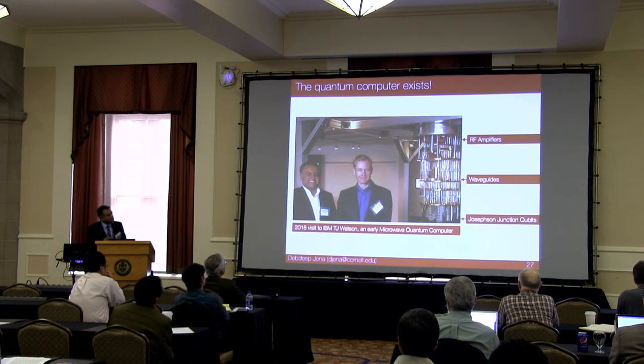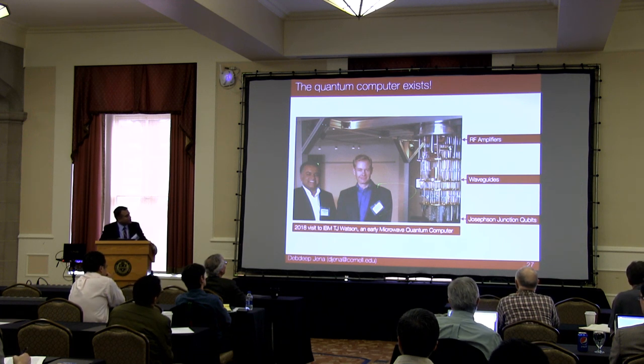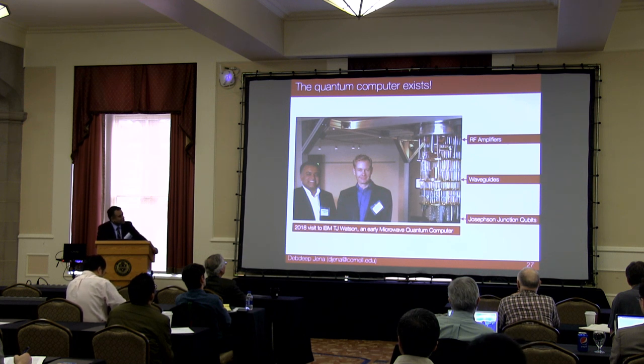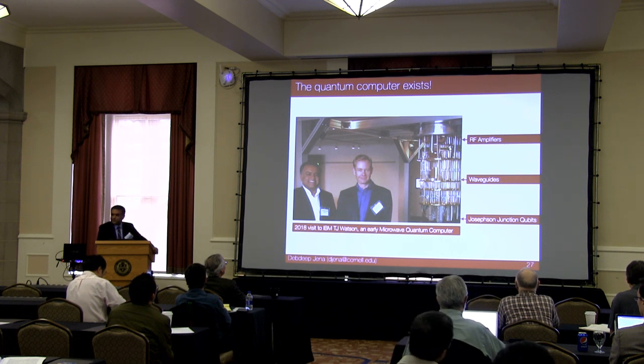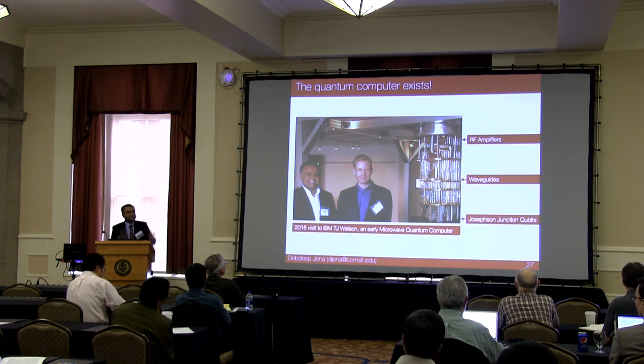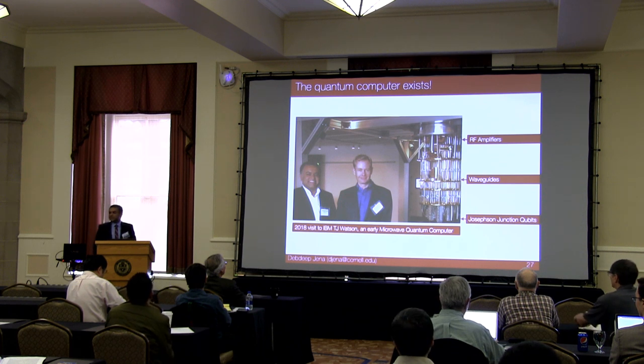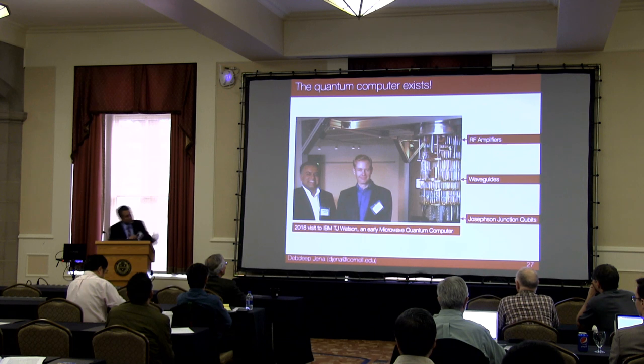And as I mentioned earlier, with the semiconductor device, we can make a transistor. So this is a completely epitaxial structure where this entire layer stack, there's a quantum well on top, there's a 2D electron gas, the entire thing is grown by epitaxy. Essentially, it's one crystal. Some layers of it are superconductors, some layers are semiconductor, they're quantum wells, et cetera. When we grew that, we have a two-dimensional electron gas on top.